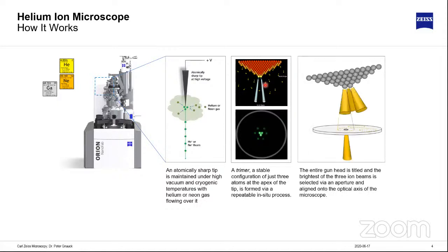And to improve that situation, we place an aperture into the beam path. We select actually the brightest of these 3 emitting atoms. And in the end, we only have an emission from 1 single atom, and that is actually the sharpest tip that you can build. And that leads to the fact that we have a brightness which is about an order of magnitude higher compared to what we have in a field emission system for electrons.